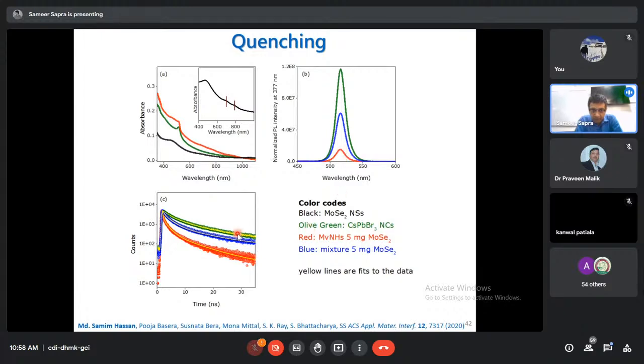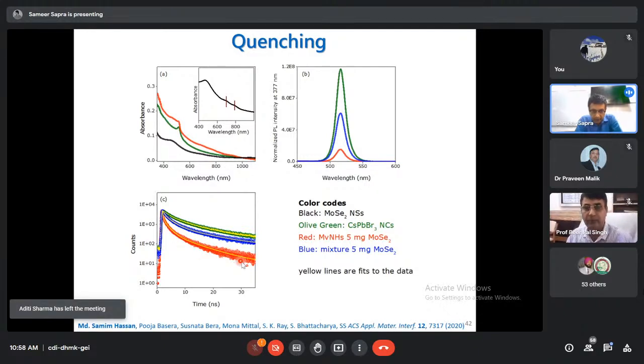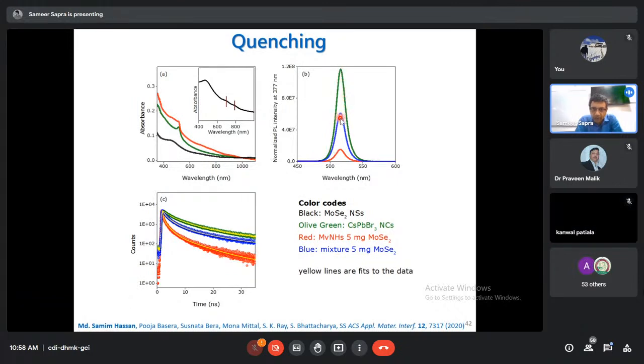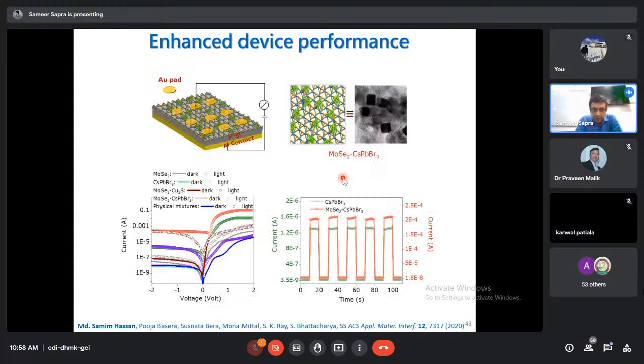And also it's evident in the lifetime, which gets quenched, which becomes much faster as you link the material. When you do not link the material, you also have a drop in the efficiency, but that is because of things dynamically coming close in solution. But the drop is not so much as when you link them and actually bring them in contact. And that is because you have a type 2 heterostructure and the electron and hole get separated and no longer can recombine to give you good fluorescence efficiencies. So you can of course make your devices with these, okay, the same photoconductive devices.